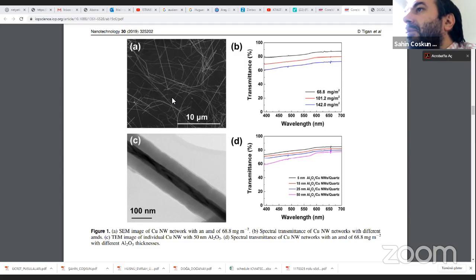It can be around 20 nanometer or something. Here the example is 50 nanometer alumina, but since those materials don't have high temperature stability, the atomic layer deposition processing is applied at a very low temperature. With some post-processing, the crystallinity can be increased, but it is really difficult.